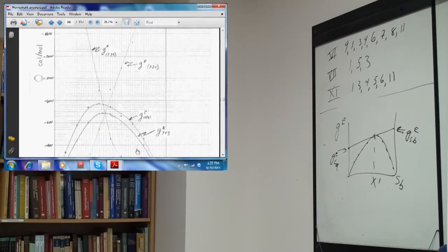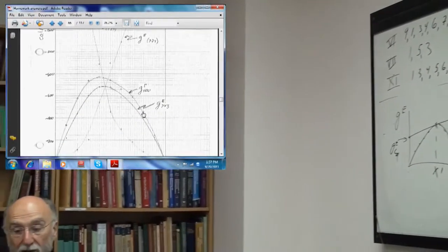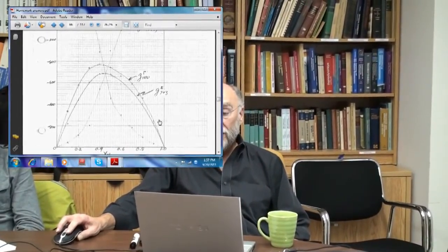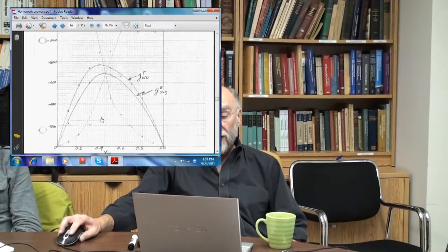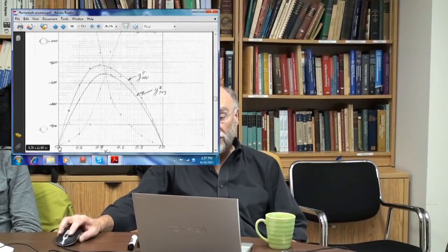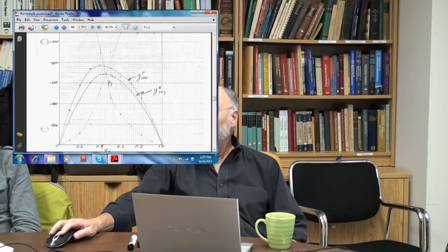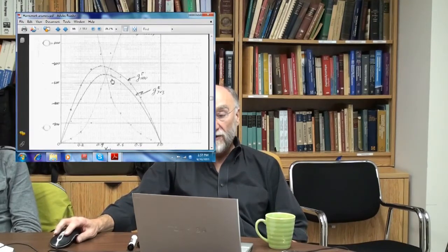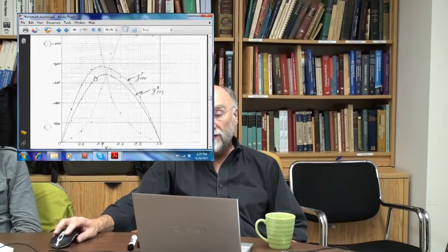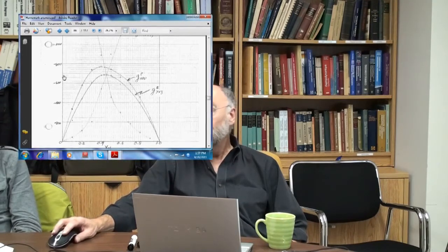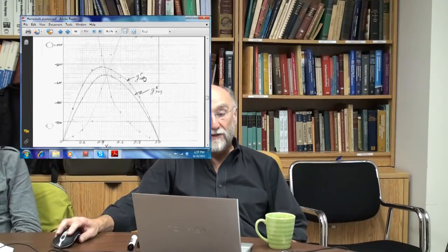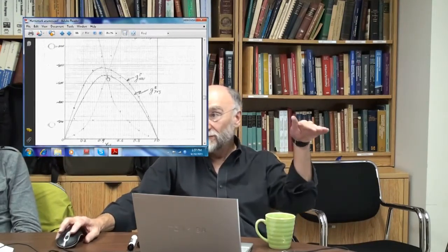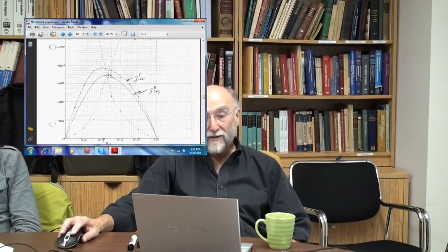I used the curve at 773, so the integral GXS goes from obviously 0 to 0. The GXS of cadmium goes from 0 here, the intercept, and then continues up. The GXS of antimony is the other intercept. Incidentally, they all three meet at the maximum point, because at the maximum you have a horizontal tangent, so the two intercepts and the integral property are the same.